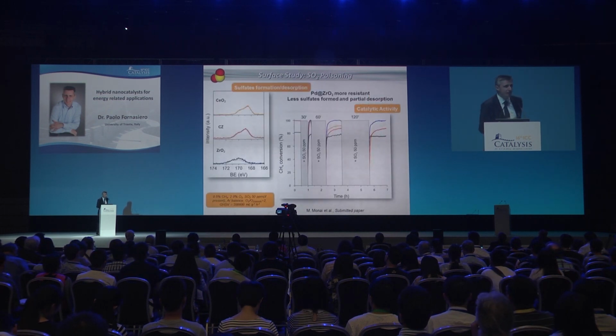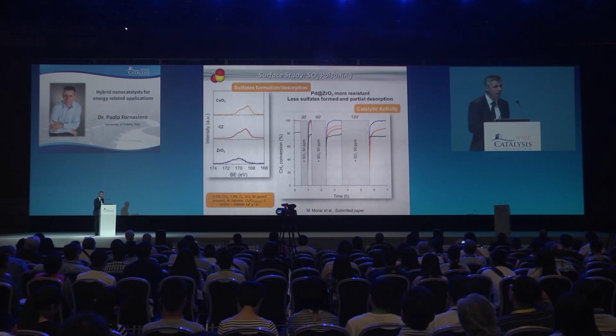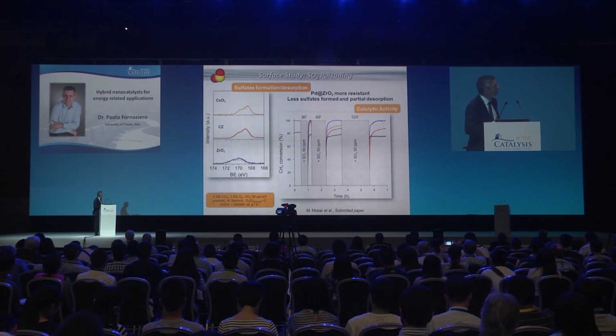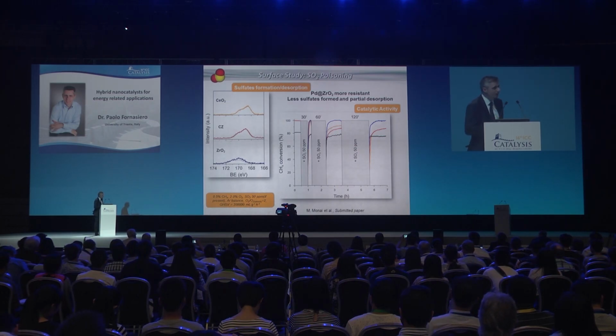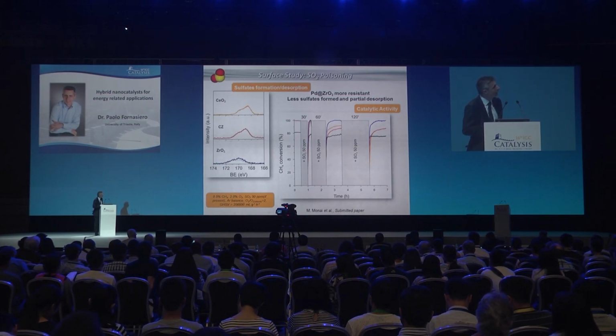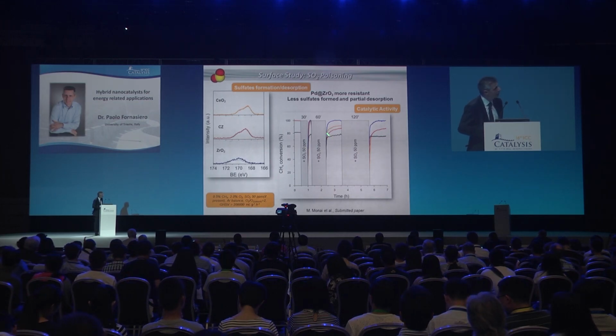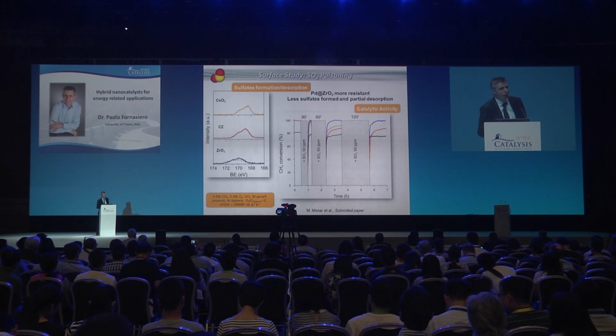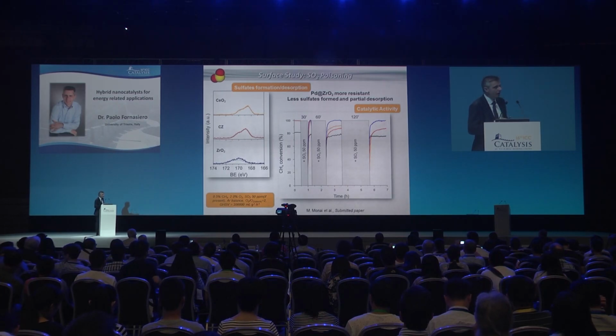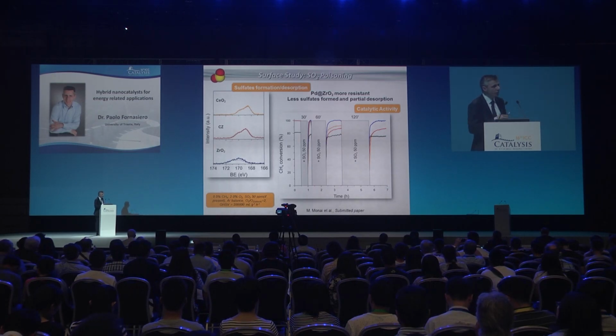And the effect of sulfur is very dramatic. At low temperature, you kill the activity of the palladium; you form palladium metal and palladium sulfate. However, at medium temperature, the effect is not that dramatic. It involves basically the shell, zirconia being less deactivated than ceria and ceria-zirconia. And if you remove SO2, the reactivation with zirconia occurs much more quickly and easily. So as a summary, ceria is good to keep the palladium oxidized, but it deactivates with water and with SO2.